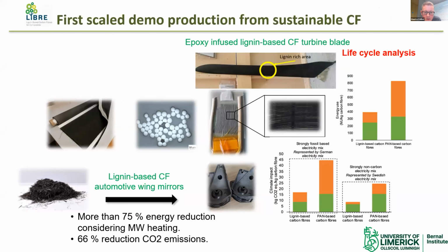These are some of the composites that we used. These are some of the first demonstrator parts ever produced using lignin-based carbon fiber. We produced a continuous fiber, infused it with some epoxy, and produced a small turbine blade. You can see it here at the top of the screen, a small turbine blade produced as a demonstrator. This was done by our partners, ORE Composites. They produced this little blade for us from continuous carbon fiber. We also produced chopped fiber: we chopped up our fibers and injection molded them with a polyamide, and we produced these wing mirrors here as demonstrators.